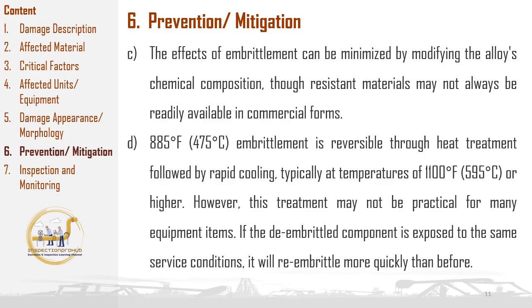One of the notable characteristics of 885 degrees Fahrenheit embrittlement is its reversibility through appropriate heat treatment. This process typically involves heating the affected material to temperatures of 1100 degrees Fahrenheit or higher, followed by rapid cooling. This heat treatment effectively dissolves the precipitates responsible for embrittlement, restoring the material's ductility and toughness.